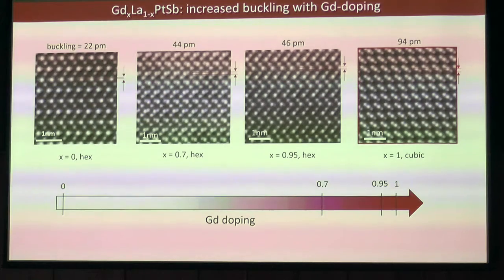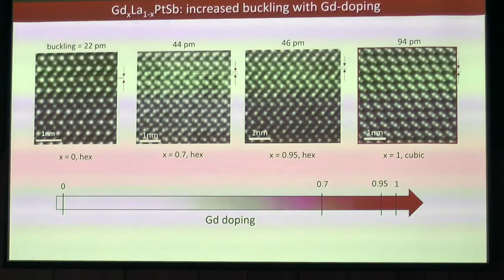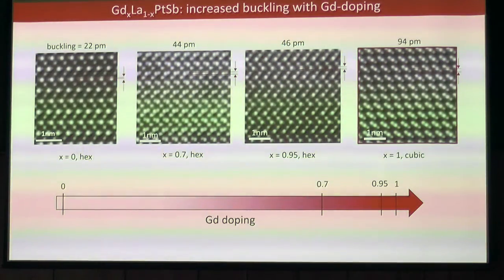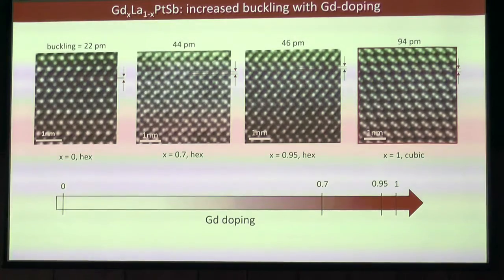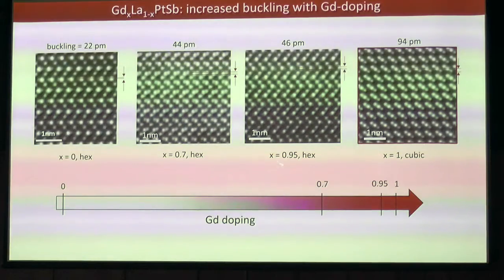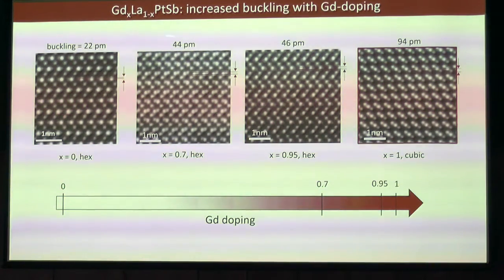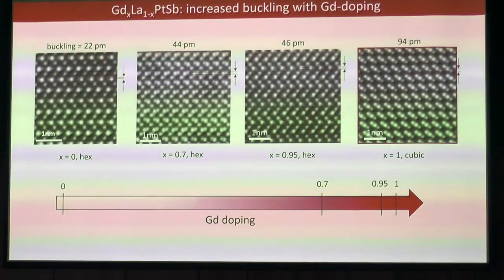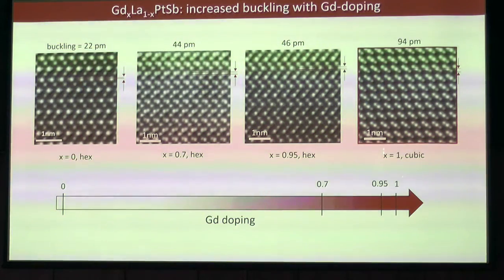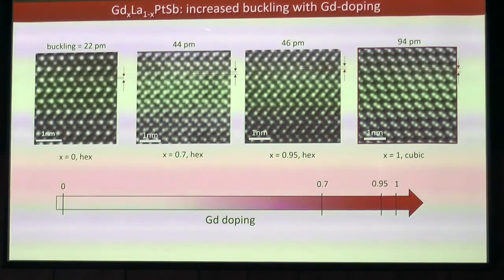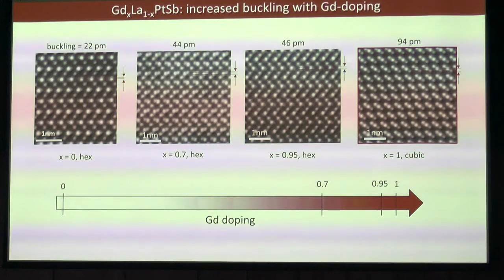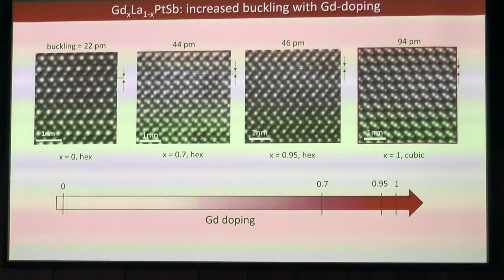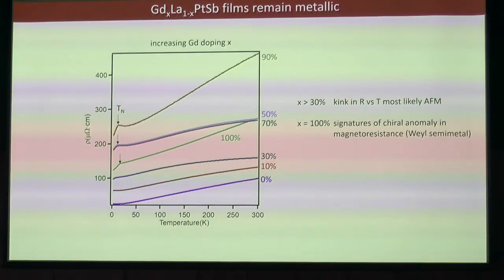So we've grown a series of gadolinium-doped lanthanum platinum antimony, going all the way from 0 to 1. In the cross-sectional TEM, we do see a steady enhancement of the buckling. From the pure phase lanthanum platinum antimony to about 95% doping, we've enhanced the buckling by about a factor of 2. Okay? And if you go too far, the stable phase for gadolinium platinum antimony is actually a cubic phase, so this has gone too far. But we've shown that you can enhance this buckling by quite a bit. Factor of 2, we were aiming for 2.5. Let's see if that was enough. Unfortunately, it was not enough.